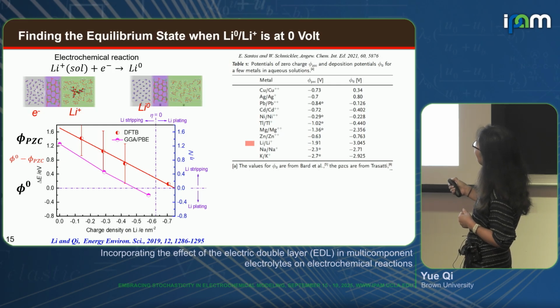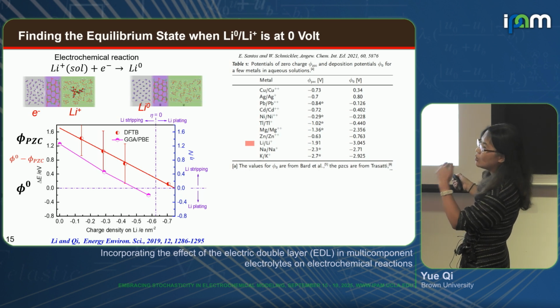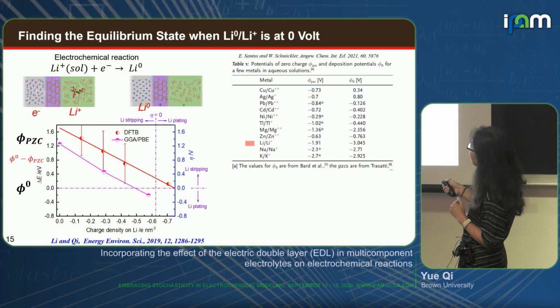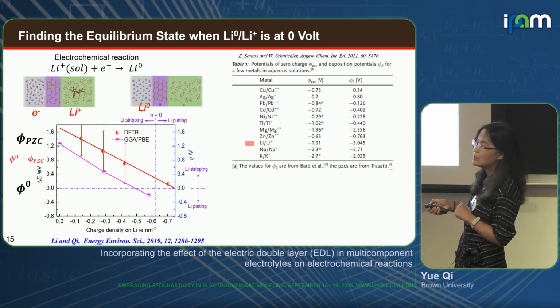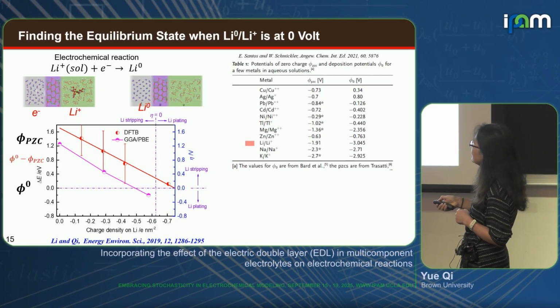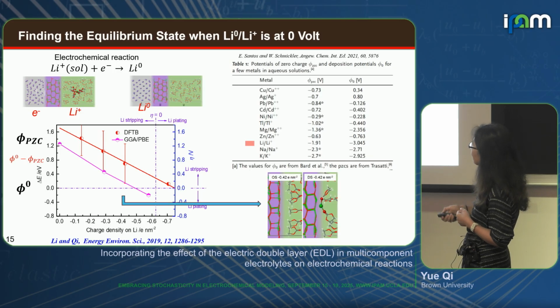I think Wolfgang Schmickler's work has been mentioned multiple times in this conference, and he actually used our DFTB parameters and did some calculations. And he also pulled out this table and said, look at this deposition voltage here, and this is the potential of zero charge, and the lithium, sodium, potassium are all below, more negative than the potential of zero charge. If you deposit copper or silver, you actually deposit above the potential of zero charge. This is really interesting, but this is measured in aqueous, it's not organic, right? So we need a whole lot of calculations and a framework to describe the complex electrolytes for batteries.